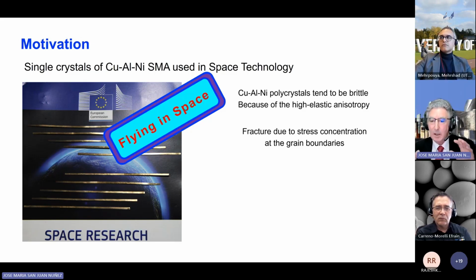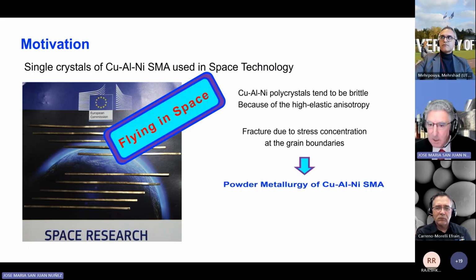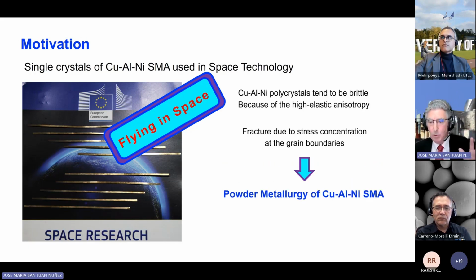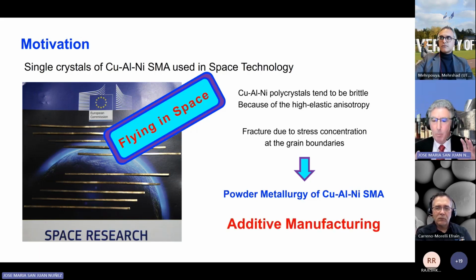To solve that, we can imagine that we decrease the grain size, and then we minimize this effect, and we can manage with polycrystals with good thermomechanical properties. So this is the idea why we use powder metallurgy of copper, aluminum, nickel shape memory alloys. And in particular now, with the development of additive manufacturing techniques, obviously we move to the production of these polycrystalline alloys by additive manufacturing. So this is the motivation.